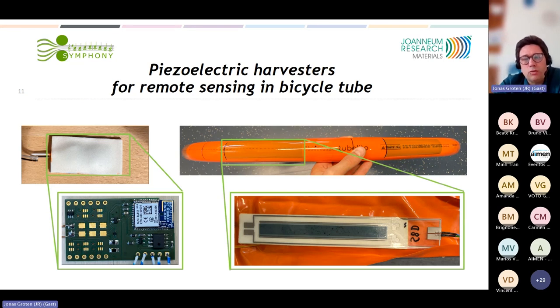we had through the company access to really put the electronics inside the tube. On the right side, you can see a nanogenerator, again, with a printed multi-layer PVDF-TrFE. On the left side, there is a small PCB with a Nordic chip transmitting data via BLE as soon as enough energy is harvested. And here the challenge really was the durability inside the tube. It's a very hard mechanical environment. And we did a lot of integration testing on the one hand, still getting enough energy by this deformation of the tube. On the other hand, making it robust and durable.